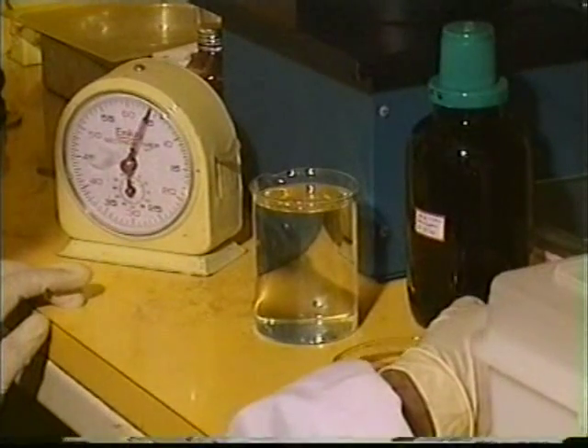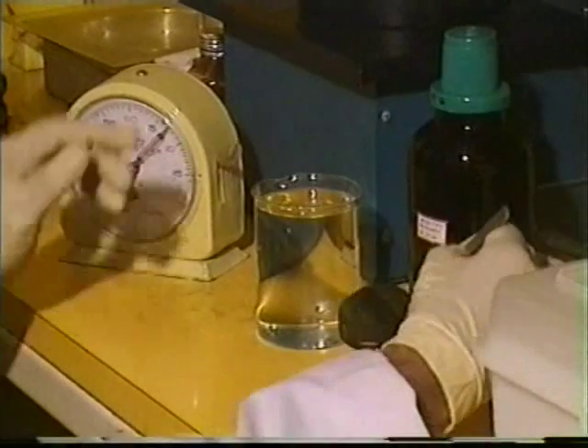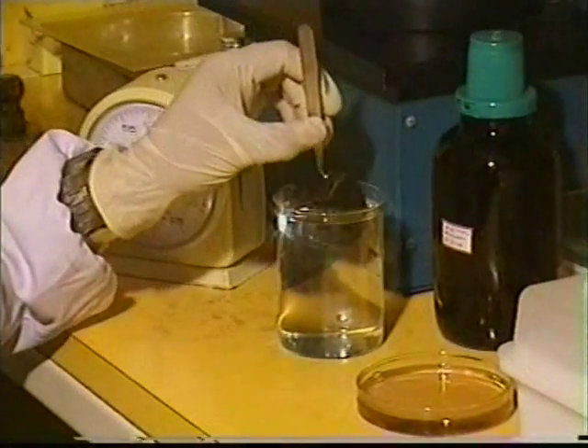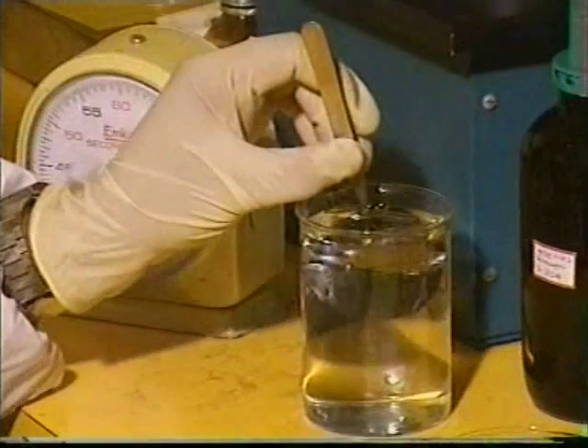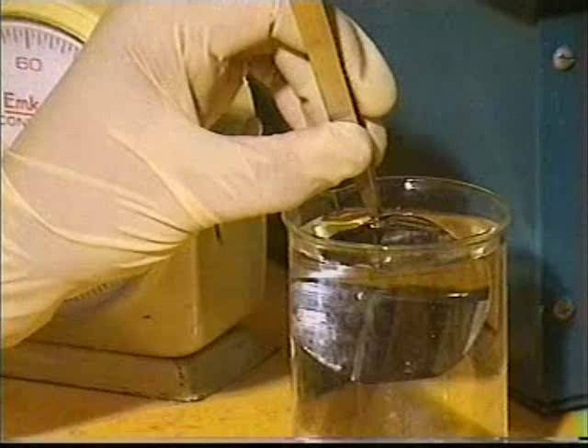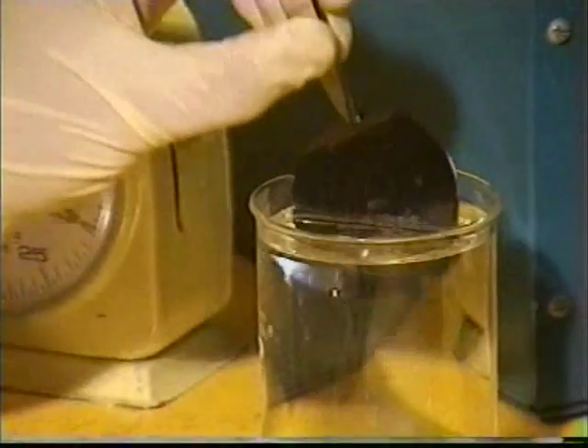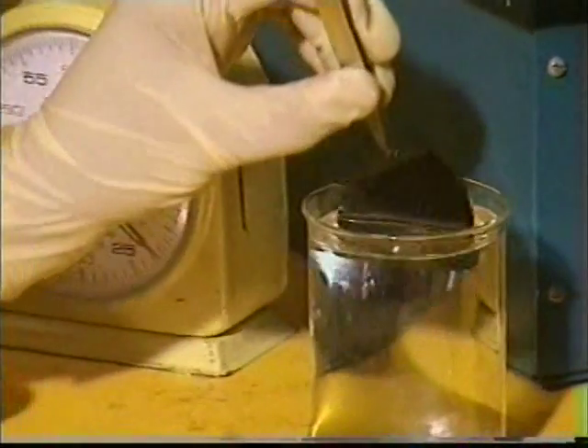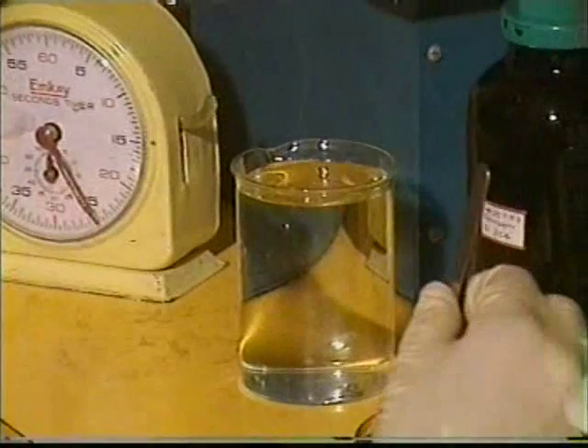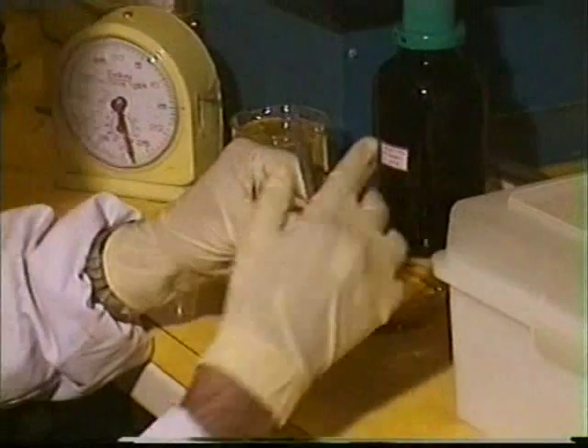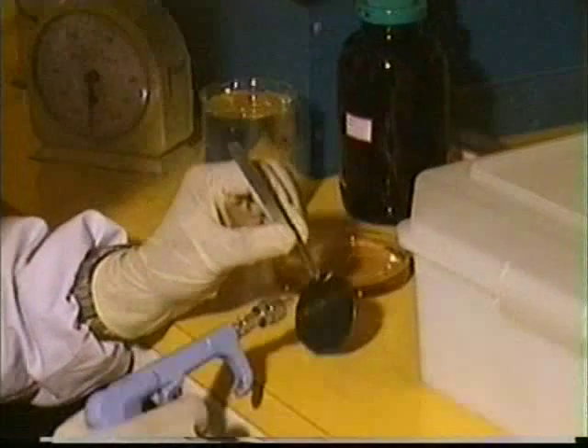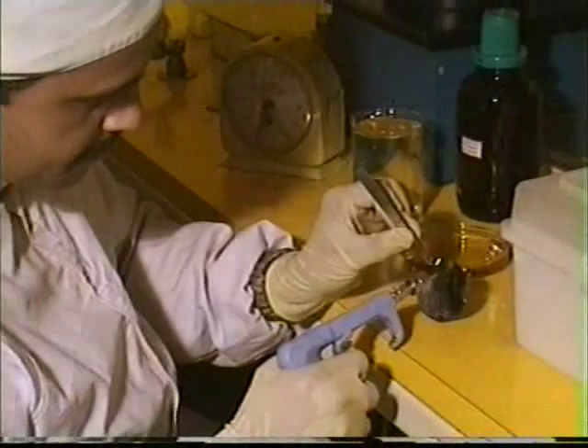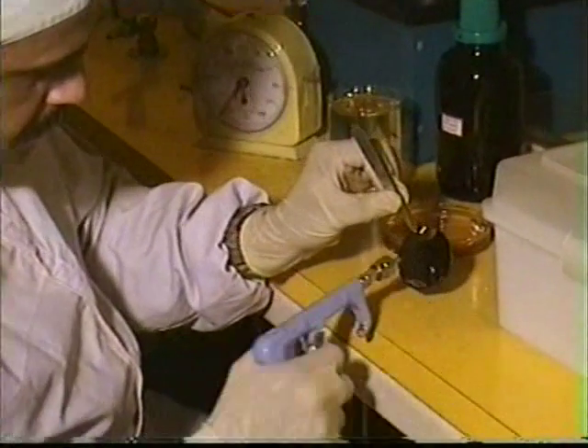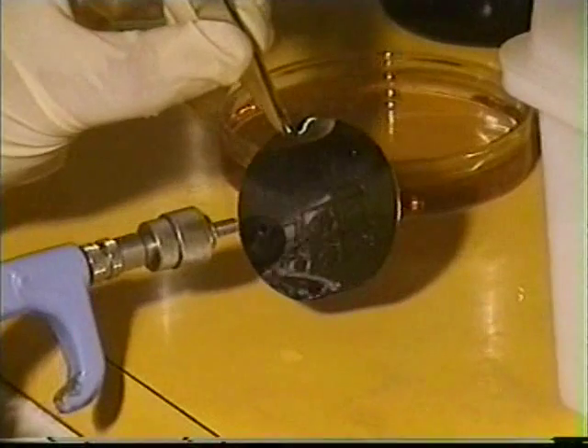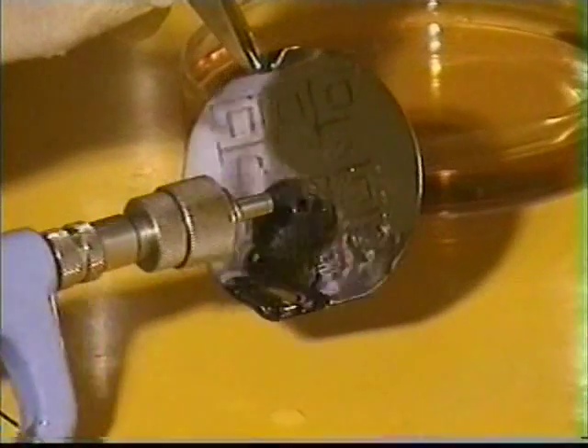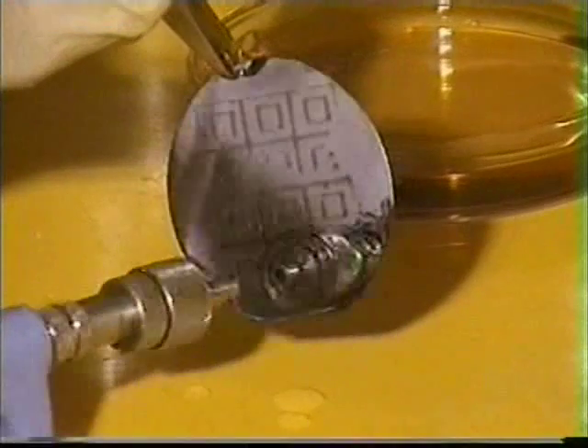The wafer is dipped in a developer solution for 20 to 30 seconds. This is followed by a rinse in DI water to remove traces of the developer solution. One can see the patterns on the wafer under a microscope at this stage. The wafer is now dried using a nitrogen jet. Please notice how the patterns emerge and can be seen on the wafer now.